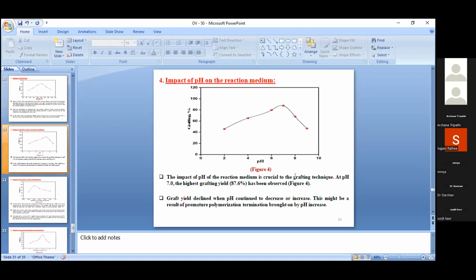The impact of pH of the reaction medium is crucial to the grafting technique. At pH 7.0, the highest grafting, that is 97.6%, has been observed. Graft yield declines as pH continues to decrease or increase, and this might be a result of premature polymerization termination brought on by pH increase.